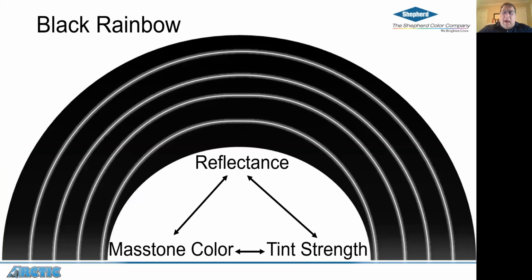At the core of that is that we have a number of different possible pigments that you can use for your applications. I like to call it the black rainbow of options, though. Even though they all look like black pigments, they all have subtle different properties. And these come down to basically a triangle of 3 different properties that you have to trade off: the reflectance, how high of a TSR you want to have, the mass tone color, how deep of a mass tone black you have, and then the tint strength. So then, depending on the application that you're looking to fulfill, what requirements you have, we can guide you with the best pigmentation for that application.